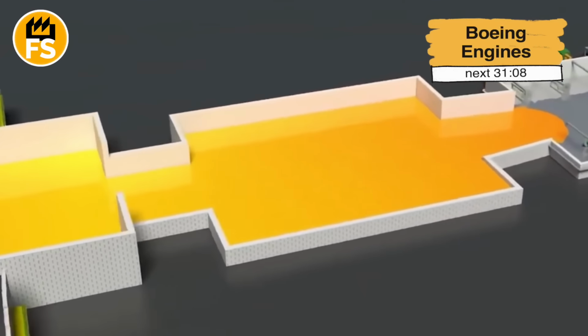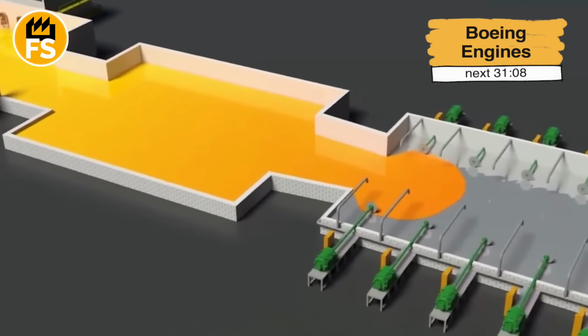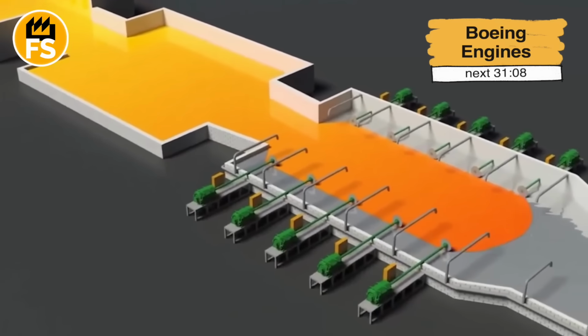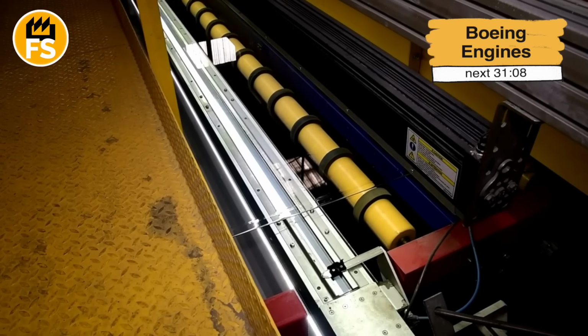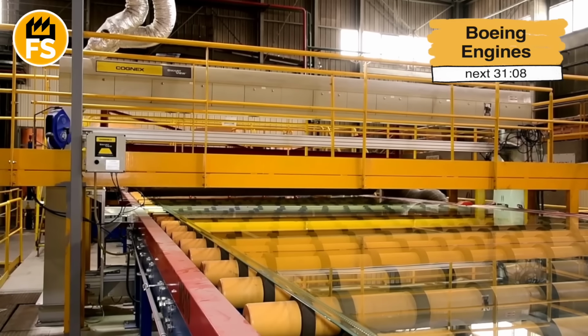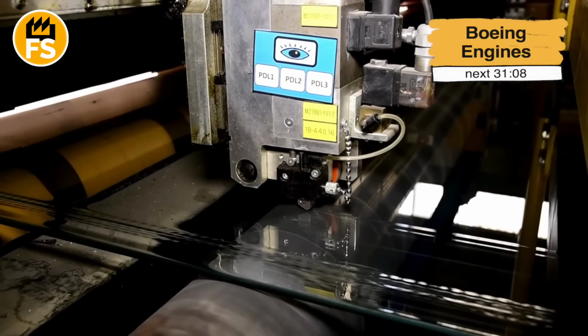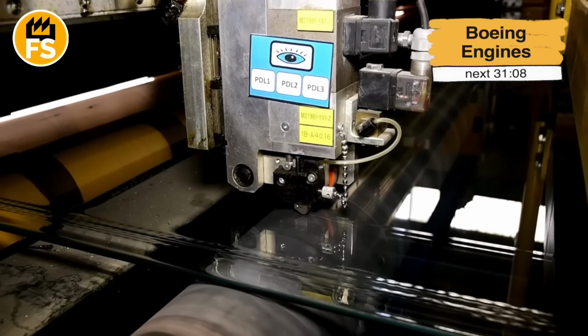the float method technology. Feeding the glass mass, the liquid glass flows out of the furnace and onto a bath of molten tin. Thanks to the high density of tin, the glass mass spreads evenly over its surface. Under the influence of its own weight, the glass forms a perfectly even and smooth surface. By gradually lowering the temperature, the glass acquires hardness. At the exit of the bath, it can already be processed. The float method allows for the production of glass sheets with precise geometric parameters and high surface quality.